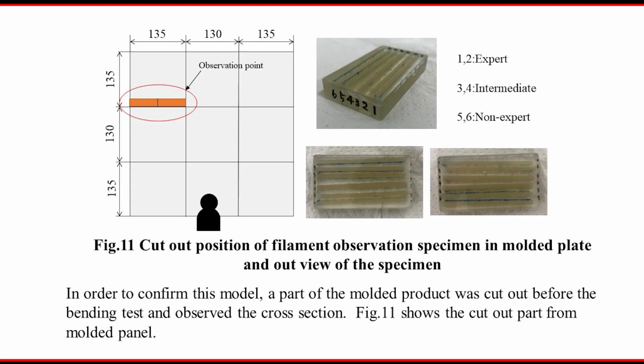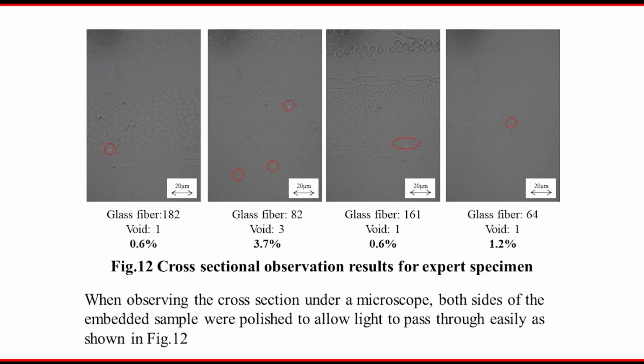So we performed a more precise observation of the fiber. This is a fiber bundle for the expert case, and for different specimens. You can find the filaments inside the photograph, and we try to count the voids, how many voids can be found around the filaments. For example, the left photograph shows 182 glass filaments, and we can see only one void around a filament. Next is 82 with void 3, 161 with void 1, 64 with void 1.